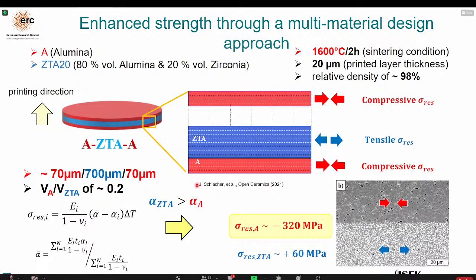We can introduce compressive residual stresses after sintering, going down from sintering temperature, when the thermal expansion coefficient of the middle layer, ZTA, is higher than the alumina layer. So these compressive residual stresses can be used. Let's say this is some kind of threshold strength, which has to be overcome to fracture the samples. So we need to overcome 320 megapascals.